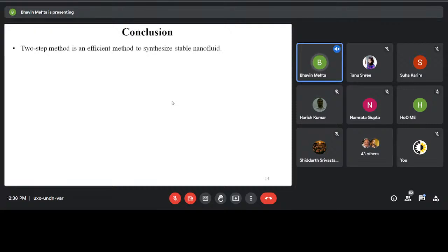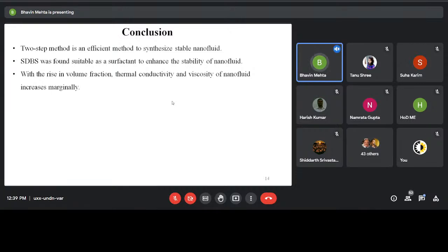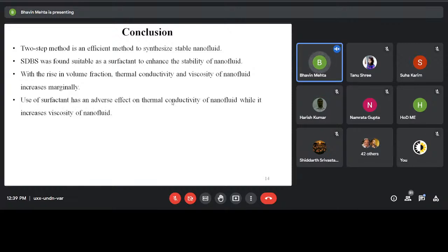So the conclusion about the experiment is that the two-step method is an efficient method to synthesize the stable nanofluid. SDBS surfactant could be used to enhance the stability. With rise in volume fraction, thermal conductivity and viscosity increase. The rise in the thermal conductivity is around 10%, while the viscosity is increased by 15 to 20%. The use of surfactant has an adverse effect on the thermal conductivity of the nanofluid.